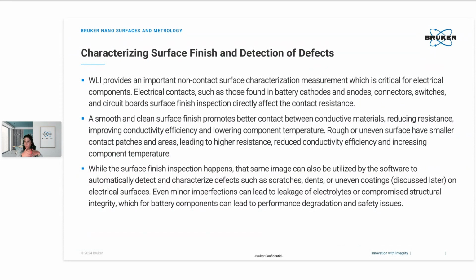This means a smooth and clean surface finish promotes better contact between the conductive materials, but also reduces the resistance, which leads to improved conductivity efficiency and a lower component temperature. In comparison, a rough or uneven surface results in smaller contact areas, which can lead to higher resistance, reduced conductivity, and also increased component degradation. Hence, the inspection of the surfaces assures the performance of each component.